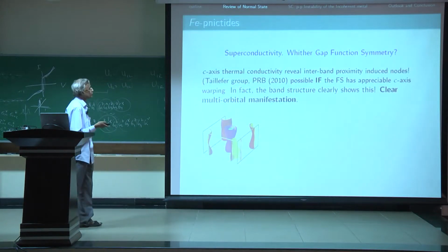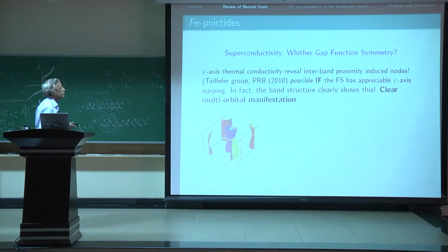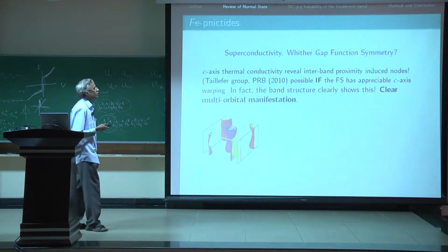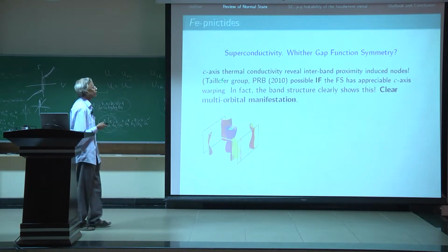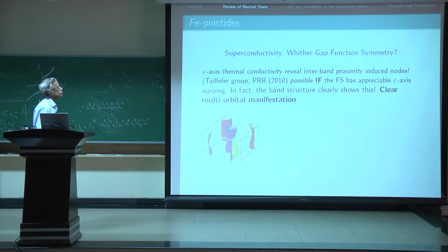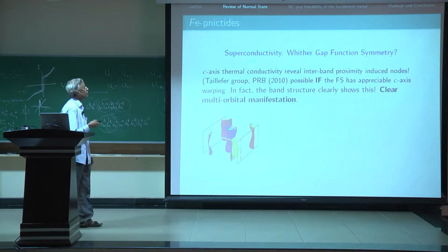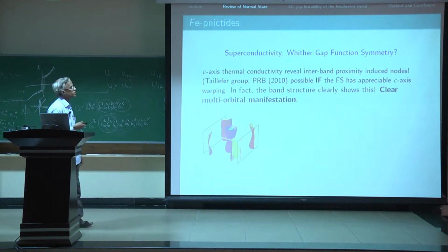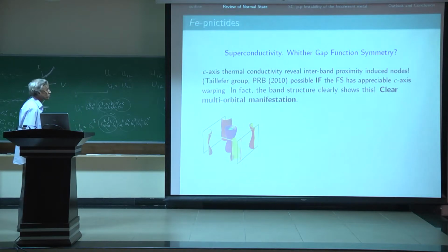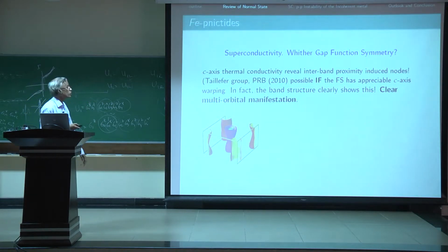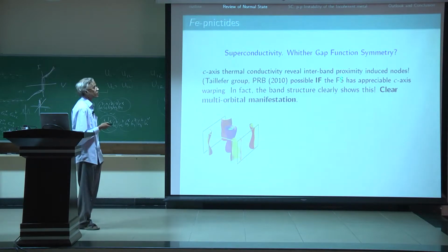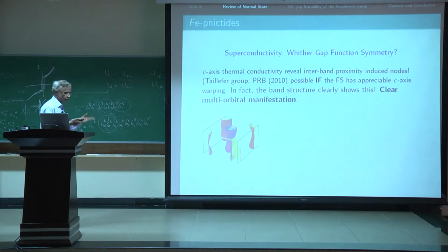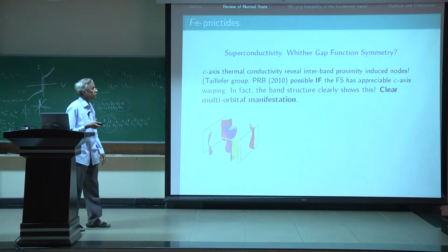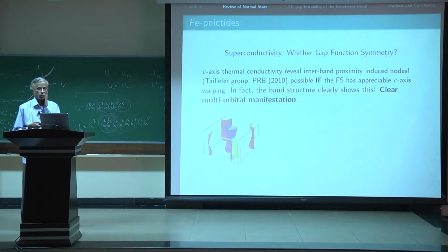All right. So, in addition, there is C-axis thermal conductivity data by the Taillefer group, which basically finds no in-plane nodes, but proximity-induced interband out-of-plane nodes along the C-axis. Because along the C-axis, thermal conductivity shows a quasi-linear power law decrease as you lower the temperature, but in-plane thermal conductivity shows an exponential drop. So there are no in-plane nodes, but out-of-plane nodes in the 122, at least. In iron selenides, on the other hand, there are no accidental nodes because the Fermi surface of the iron selenides has very little warping along Kz. So there is a direct correlation between the kind of Fermi surface you have and whether you have accidental gap function nodes or not.